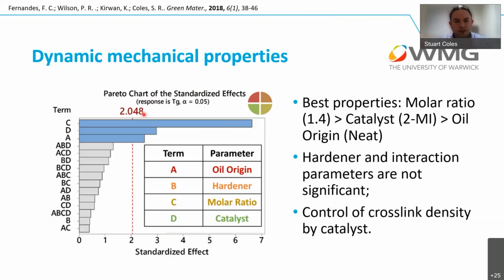We did, however, continue to look at the statistical analysis to see what were the important properties, and it was found that the interactions between all of our different parameters weren't significant based on a standard significance test. What were the important factors? Was whether the molar ratio was high or not. We got the best mechanical properties at that high molar ratio. It did impact the thermal side, but the mechanical properties were best at that high molar ratio.